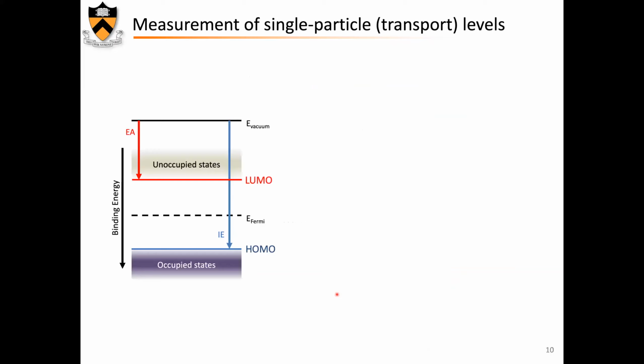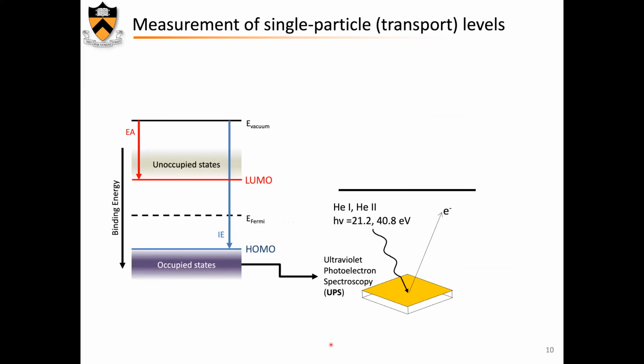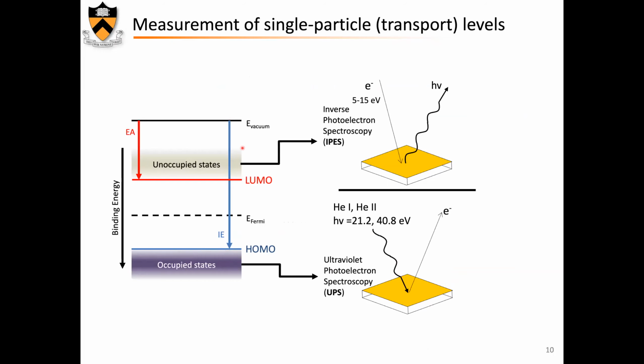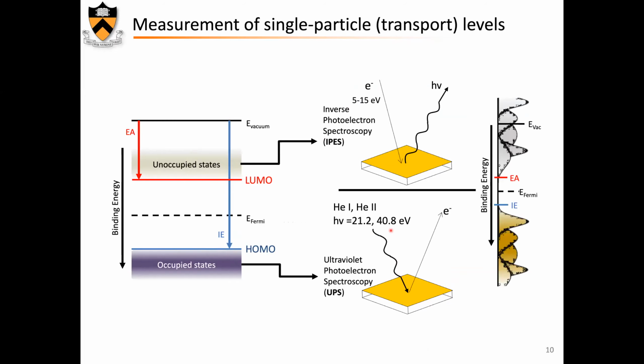Okay. So one has to go and measure these, and they are typically measured with either ultraviolet photoemission spectroscopy that looks at the occupied states, or inverse photoemission spectroscopy that looks at the empty states, and that leads to a complete picture of the density of states: the valence states, or the highest occupied molecular orbital, and lower level, the band gap, and then the unoccupied states, density of states up there.